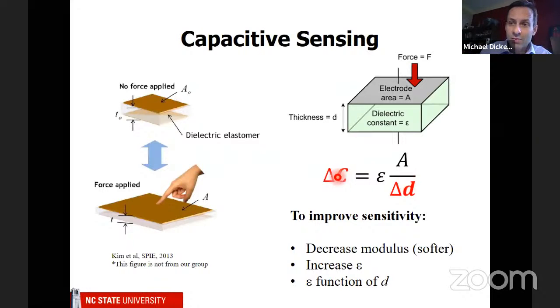So if you want to make this thing really sensitive, what you want to have is a low modulus, so that it's very easy to press this. You want to increase the dielectric constant. This is kind of a challenge because most soft materials have very low dielectric constant. And one thing that would be really cool but difficult to do is to make the dielectric a function of D. So as you squeeze it, the dielectric would increase or decrease.